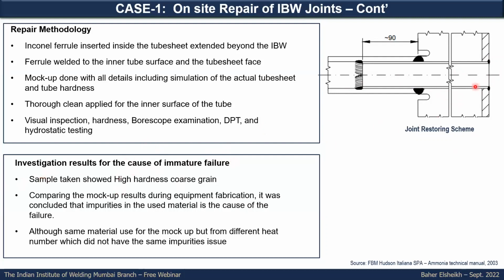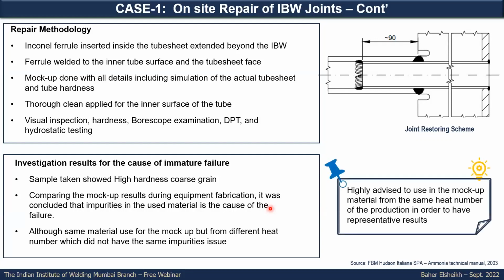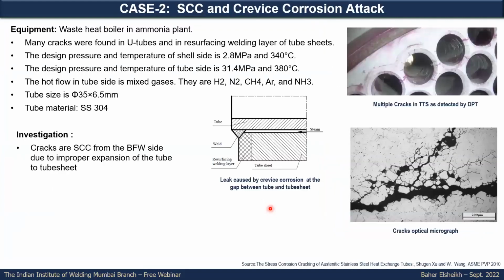During the investigation, they took a sample from the failed tube, and the conclusion was that it was actually in service for a short time, and that the failure was related to improper application of the initial mock-up during the equipment fabrication. They used a similar tube sheet material, but not from the same heat number. When they used a sample from the actual failed tube sheet, they found coarse grain, high hardness and some impurity material in the tube sheet. So if during the mock-up you use the same part or a part from the production material itself, you will have representative results and avoid such an issue.